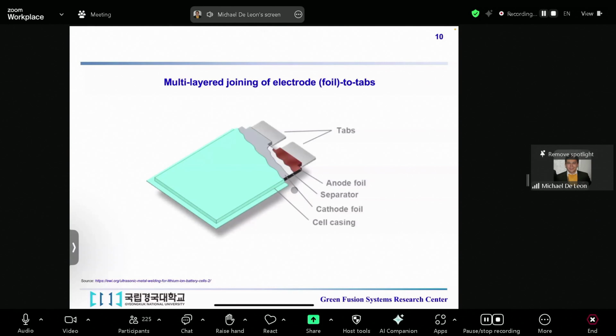Since standardized tests for multi-layer ultrasonic welds don't exist yet, we developed an evaluation protocol. Joint strength was measured using a custom peel test that applied controlled peeling forces at 20 millimeters per minute through a 5 kilonewton load cell tensile test machine, across 3 critical weld interfaces: single layer, 2 layer, and 3 layer bands.